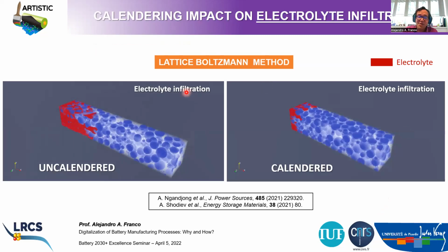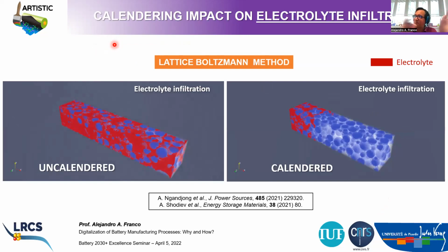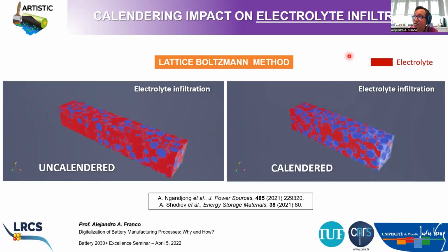Well, this is what you see here. This is the macroscopic view of the result of the LBM. Imagine that there are plenty of tiny particles moving there, but you have the feeling that this is a continuum. And you see the result for the infiltration of electrolyte in an uncalendered electrode, which is very quick, and the simulation of the infiltration of electrolyte in a calendered electrode, which is very slow. The reason is that in a calendered electrode you have a higher tortuosity factor, right? Pores are interconnected with each other, but the more tortuous the path, the more difficult it is for the electrolyte to go through. So this is something that the model can recover very well. This is good news, but kind of trivial.